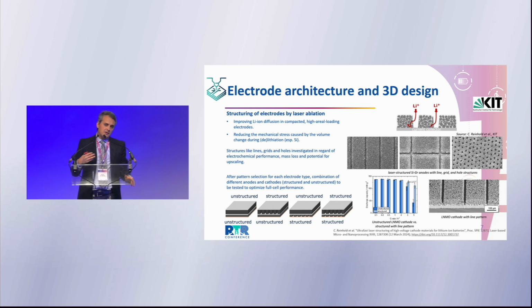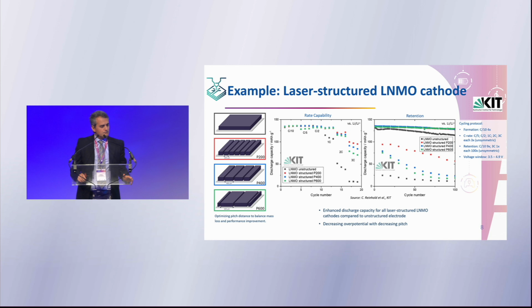We don't see a big advantage when we compare laser-structured electrode with non-laser-structured electrode up to 1C. We do see an advantage at 2C, but we really see that 3C and 5C is where this technology gives a lot of advantage. This is very, very interesting, and we are pretty much happy with these results. This is something that we can extend also to the anode. The results that you see here are at the cathode. And specifically, this is a technology that we can extend also to other chemistries. So this is something that is reusable across generation 3 and generation 4.